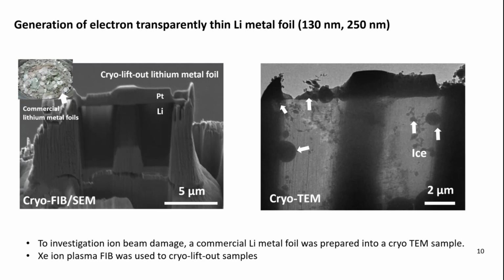During this step, you have to purge your vacuum tool so that you can take the sample from the vacuum to ambient conditions. During these steps, you have to purge your vacuum transfer tool with dry nitrogen and liquid nitrogen. At some point, the door for the vacuum transfer will be open to ambient conditions. At this time, you have a lot of humidity sources, so a trace amount of humidity can be attached to your samples. If your shuttle or cryo transfer tool has an anti-contaminator to protect your sample from water condensation, that would be ideal. But to my best knowledge, in the Leica Microsystems, we don't have an anti-contaminator for the materials science-based shuttle. So that's where we have a lot of ice condensation.